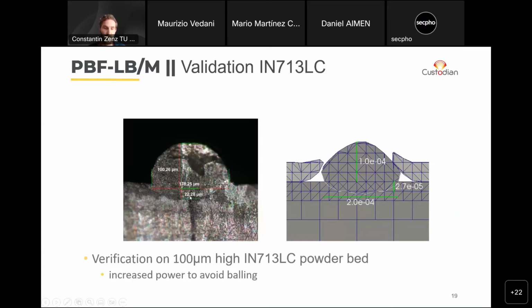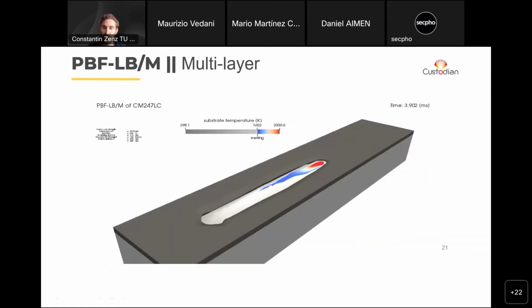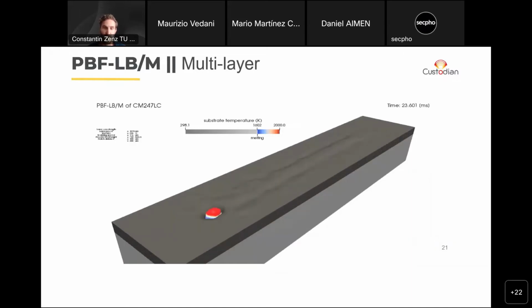So after adjusting the power, increasing it, we obtained these results, which you can see here, the experiment, and then again for validation, the simulation result. And after obtaining a good reference in this way, we performed a similar optimization study like for the CM247LC material. And then what we also did is we looked at not only multi-track, but also multi-layer simulations, because in the end, for an industrial process, we also, of course, want to go towards real part production.